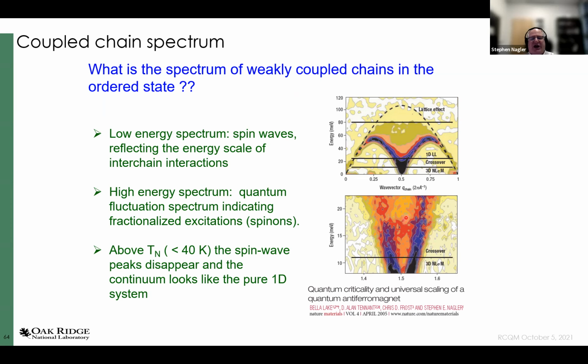And at a slightly higher energy, I will see something that's basically a longitudinal fluctuation, unlike the spin waves that are transverse fluctuations. These days, we would call that the Higgs mode. And at higher energies, I still see signs of this continuum of excitations coming from the fractional excitations. But the point is this: if you're at low temperature and the system is actually ordered, you will see quite possibly a coexistence of sharp modes and broad modes.